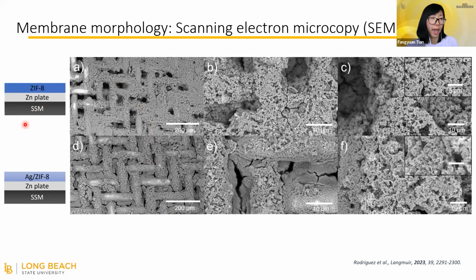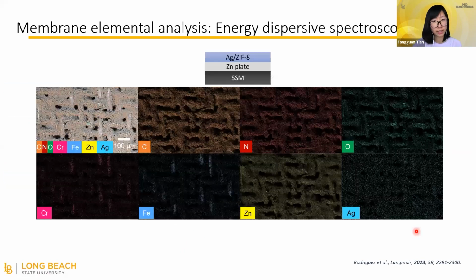And once we add the ZIF-8 solution and repeat this electrodeposition, you'll notice there are lots of ZIF-8 particles coated on the surface. And the silver ZIF-8 system doesn't look quite different from the ZIF-8, but when we compare the EDS, the elemental analysis, we notice that there's silver all over the surface. This picture shows the silver elements in the blue color.